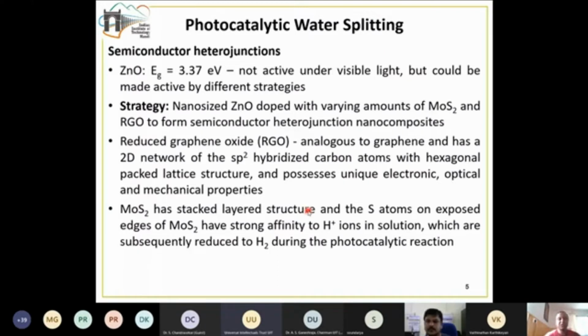In this regard, we chose zinc oxide, because it's easily available, non-toxic and low cost, and it has a band gap of about 3.37 electron volts. Hence, this wide band gap material is not active under visible light, but there are different strategies one could adopt to make this material more active. One of the strategies that we adopted is that we doped it or made a composite of zinc oxide with varying amounts of MoS2. MoS2 is another very interesting material which we will be seeing. MoS2 is molybdenum disulfide, and then another is reduced graphene oxide, in order to form a ternary semiconductor heterojunction nanocomposite. Why ternary? Because it has three components: zinc oxide, MoS2, and RGO.